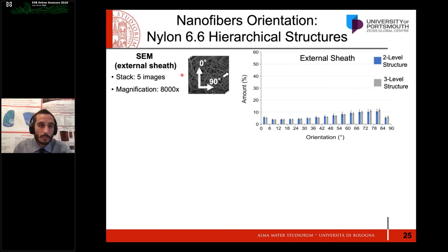We take some SEM images of the electrospun membrane, and then we apply the directionality plugin as previously shown. Here you can see in gray the three-level structure results, and in blue the two-level structure one.